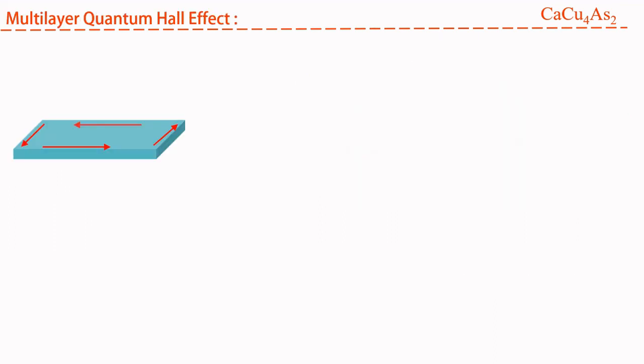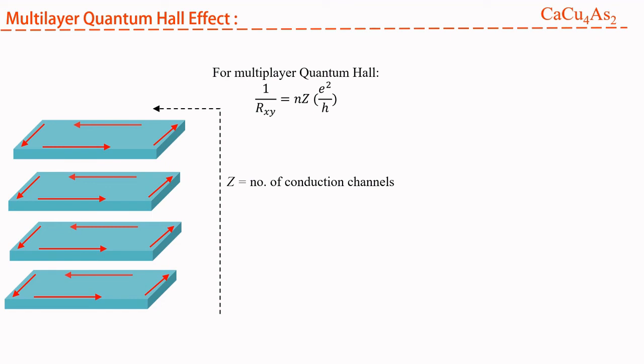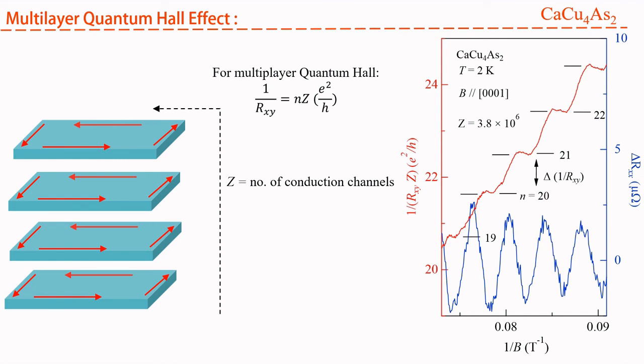In 2D system, high magnetic field leads to dissipationless edge state, producing quantum Hall effect. For multilayer transport, the large number of conduction channels contribute to Hall resistance. Here Z indicates the total number of conduction channels in the system. Here is our inverse Hall resistivity data, which shows quantized Hall step.